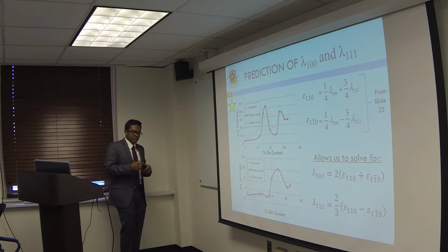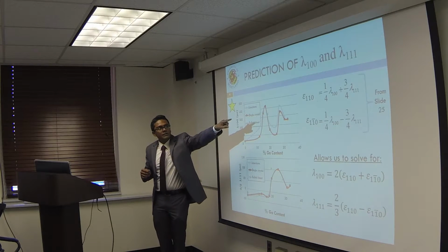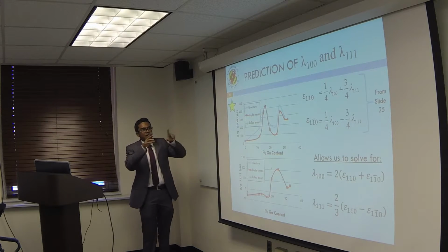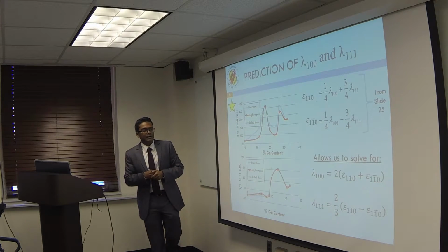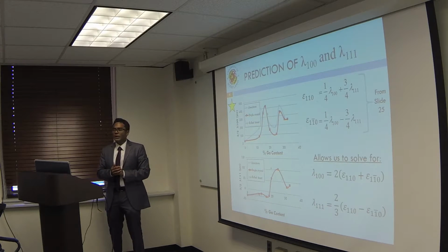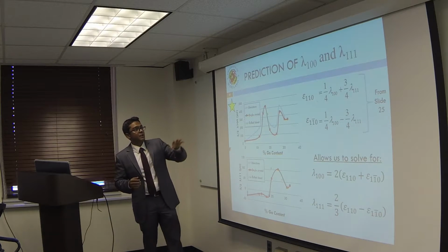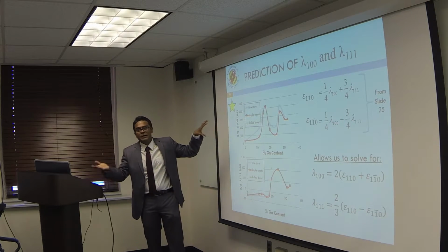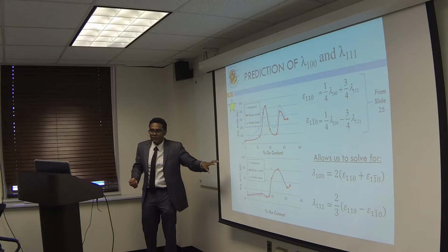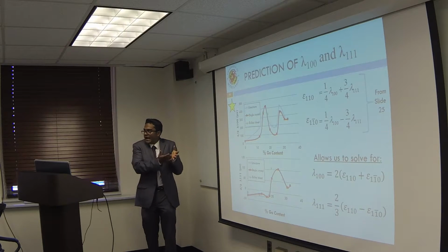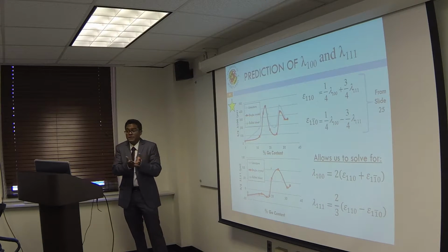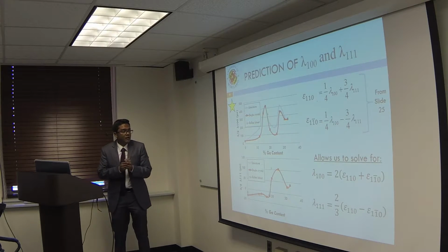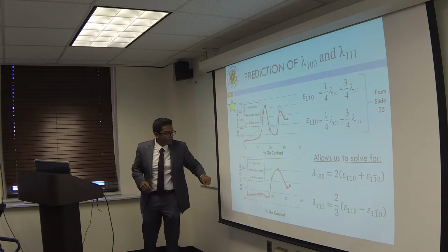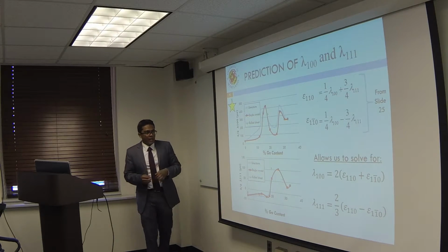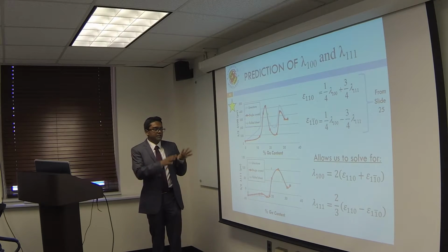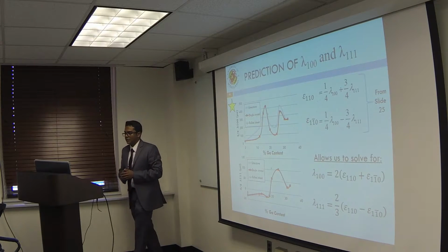So what else can we do with the results that we obtained? Using the values of longitudinal and transverse strain at saturation, you can actually play around with the numbers and be able to predict the values of lambda 100 and lambda 111. It just allows us to solve because we have two equations and two unknowns. This is really interesting because now we can, well, it's not predict, it's experimentally determining the values of lambda 100 and lambda 111, which are the fundamental magnetostrictive quantities, by having values of strain at magnetic saturation along the diagonal instead of along the edge of the cube. As you can tell, there is pretty good correlation in both the values of lambda 100 and lambda 111 when compared with literature. And this is the first curve that populates the lambda 111 curve for 20 samples of Galfenol.